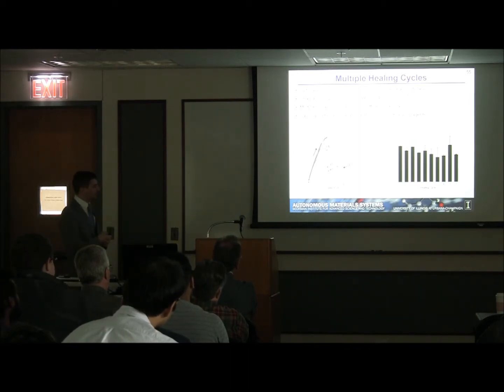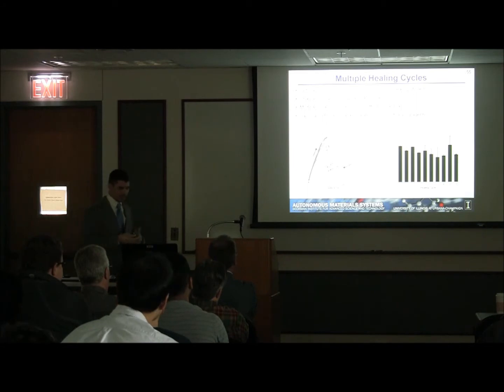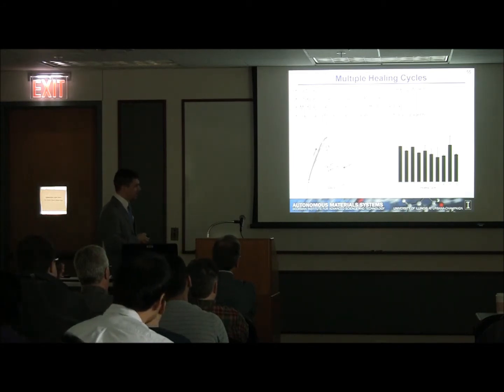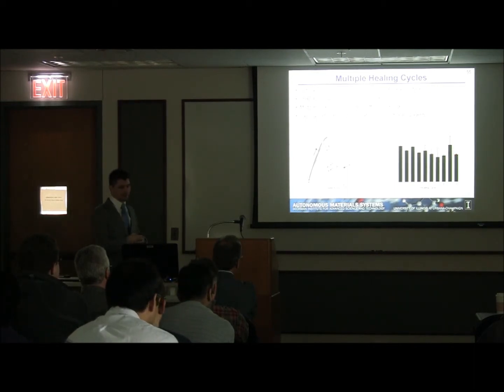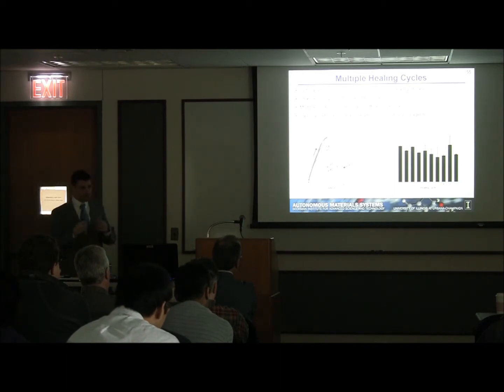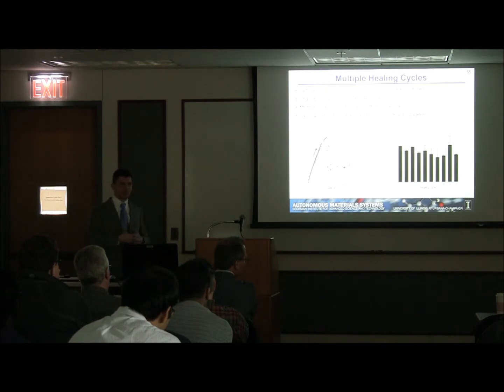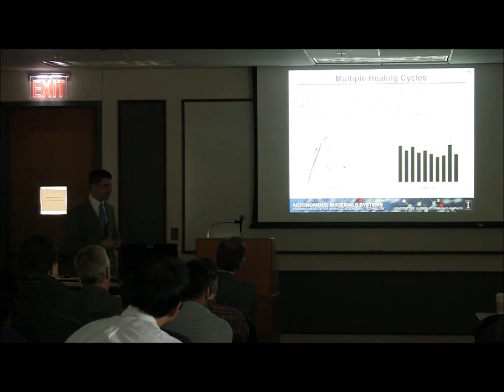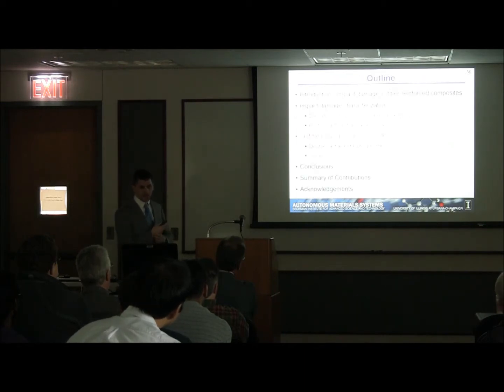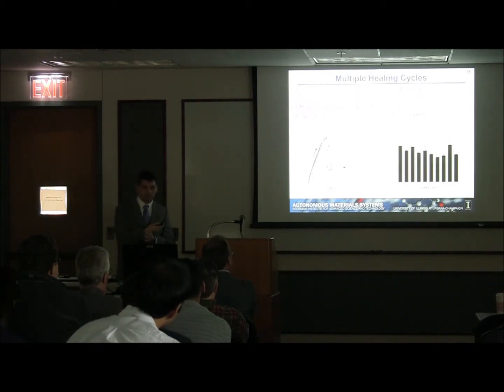When we apply the best healing agent delivery, we do see repeat healing is possible as long as the channels are clear, and we're able to show up to 10 cycles of healing with roughly between 50 and 65% efficiency. This really is the first demonstration of 10 multiple healing cycles, taking advantage of the vascular redelivery over and over to the same area of the crack plane inside of the specimen. I think this was one of the better accomplishments of my time here at Illinois. So, to continue with my outline.